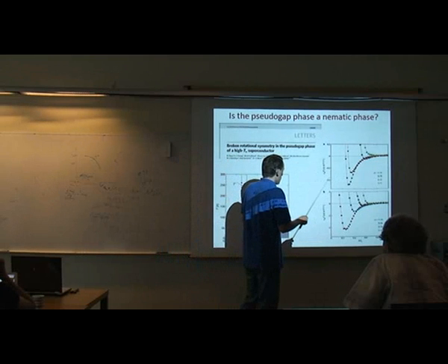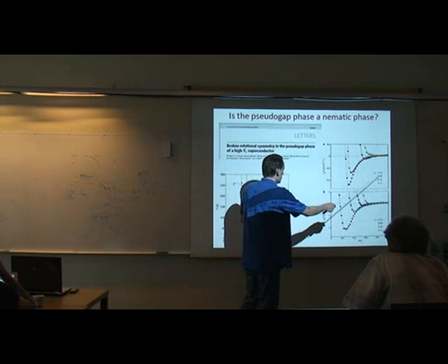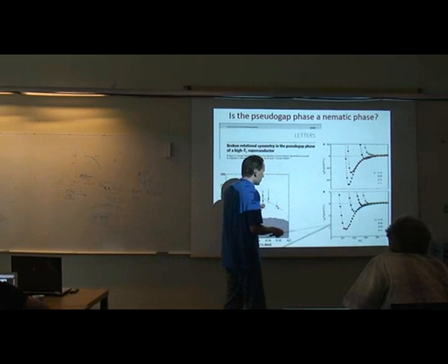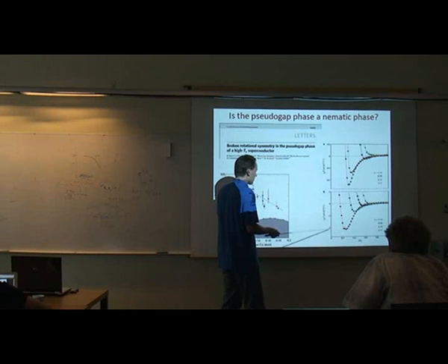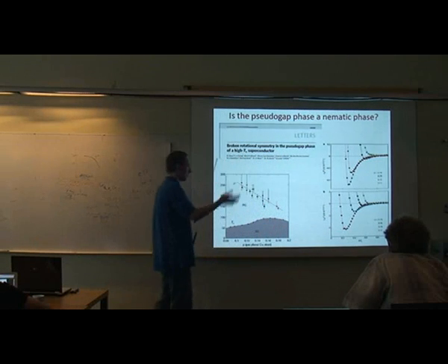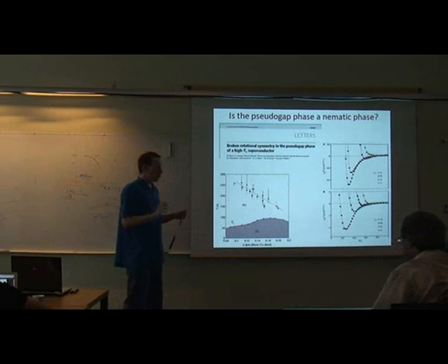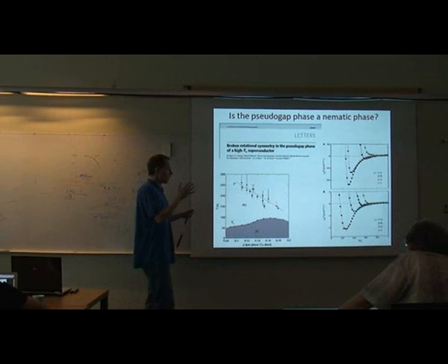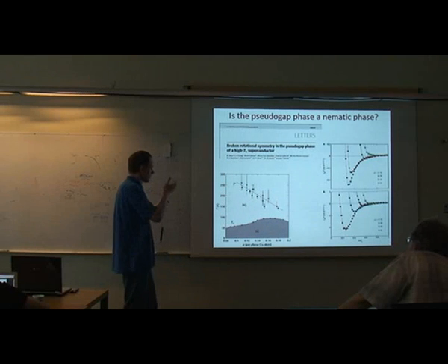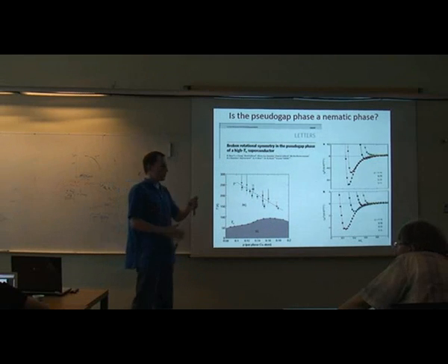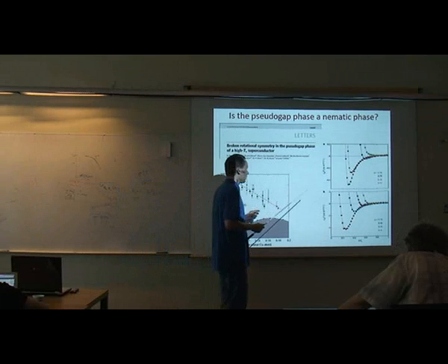And you see the size of the signal for all these dopings seems to be 1 order of magnitude different. So it's a factor of 10 anisotropy of the signal, which is very spectacular if you consider the conductivity, which is very much less anisotropic. And it's very much less clear whether it's a nematic phase or just the copper oxygen chains, which produce this anisotropy.